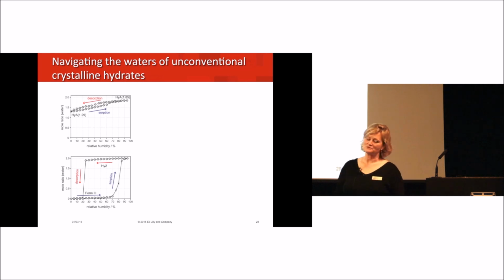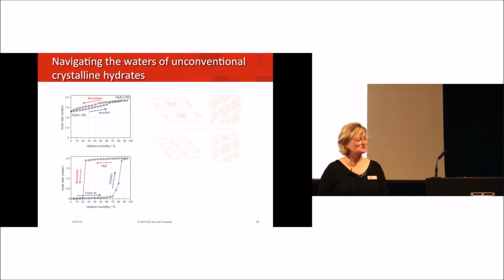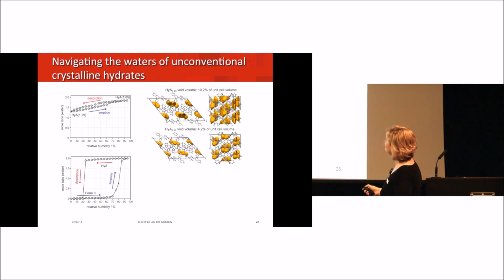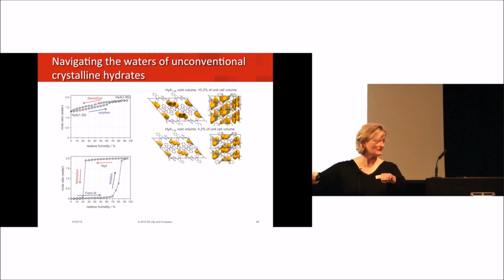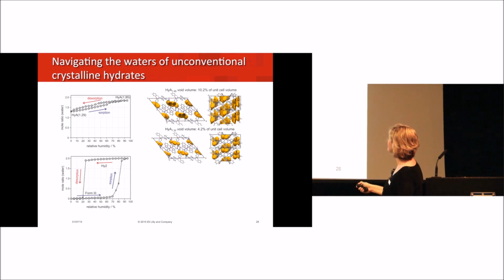I just want to give a shout out with respect to the DB7 compound to some work we did around the hydrates and bring myself back to the very first example. Because in the DB7 compound, we have two hydrates, one of which is a stoichiometric hydrate, retaining about 2 molar equivalents of water in the structure. And the other one, if you look closely, is a nonstoichiometric hydrate. And if we come back to the solvent pores, much as in the first example, what we find is our nonstoichiometric hydrate does not have continuous channels. These are pockets that as you remove water from this crystal, the unit cell contracts, and the pockets become farther and farther apart. And so what happens is when you get to the low end of the humidity range, it becomes increasingly difficult to pull those molecules out.